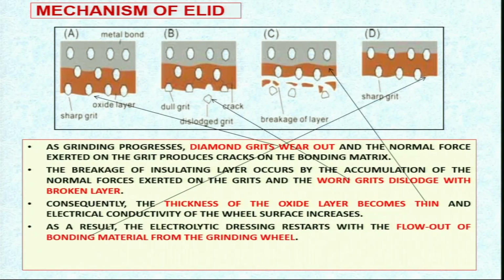As a result, the electrolytic dressing restarts with the flow out of bonding material from the grinding wheel. Once this flow out or removal of the bonding material starts, the worn grits are removed and fresh abrasive particles protrude outside, and the oxide layer formation further takes place, and as you can see this oxide layer has increased, but the sharp abrasive particles are protruding.